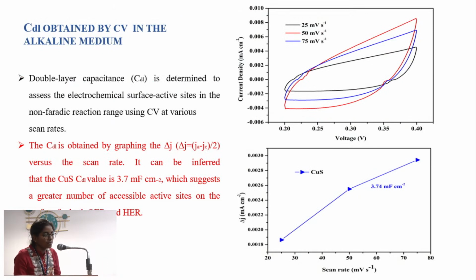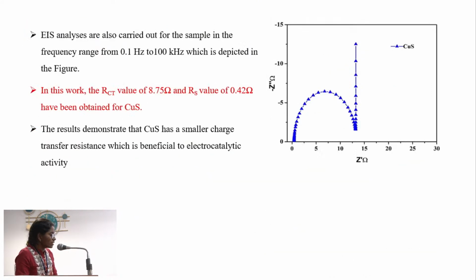To calculate the electrochemical active surface area, I have performed CV in the non-Faradaic region at different scan rates. Through the CV, we can confirm the double layer capacitance of the material. Through that, we can measure the electrochemical active surface area. I have plotted the delta J values against scan rate and obtained a double layer capacitance value of nearly 3.74 millifarad per centimeter square. This is a good capacitance value for a binary compound. And through electrochemical impedance spectroscopy, I have measured the charge transfer resistance and series resistance of the material. A series resistance of 0.42 ohm and a charge transfer resistance of 8.75 ohm have been measured. The low charge transfer resistance is due to the highly enhanced electrocatalytic activity of the material.